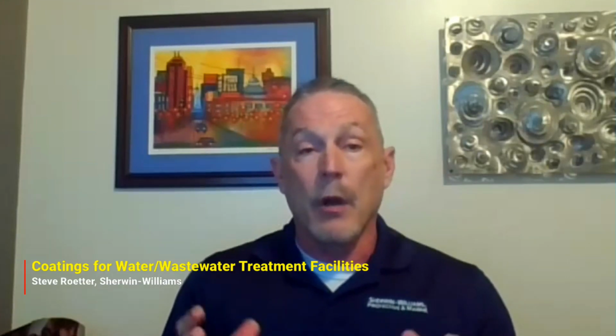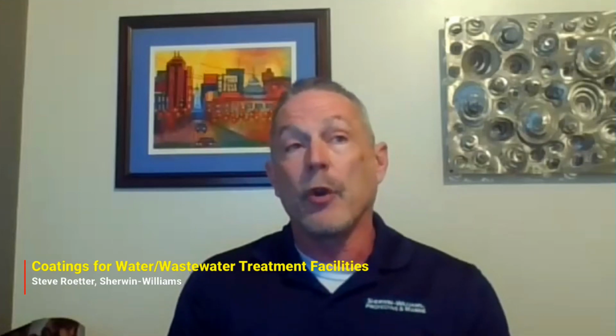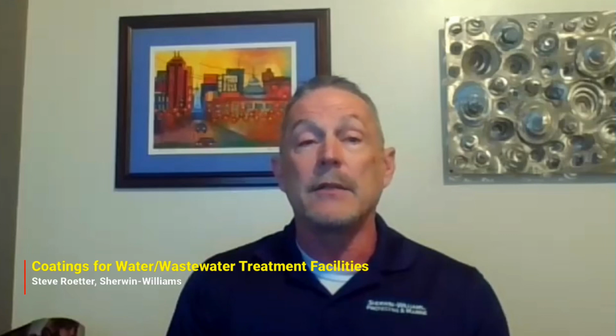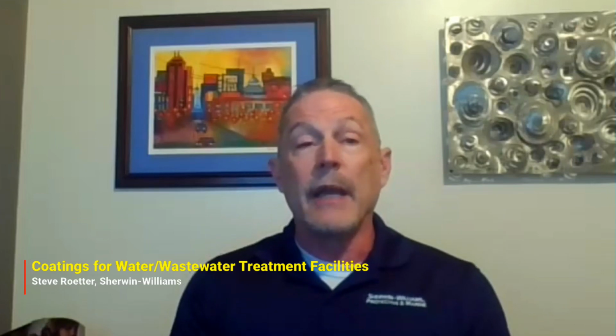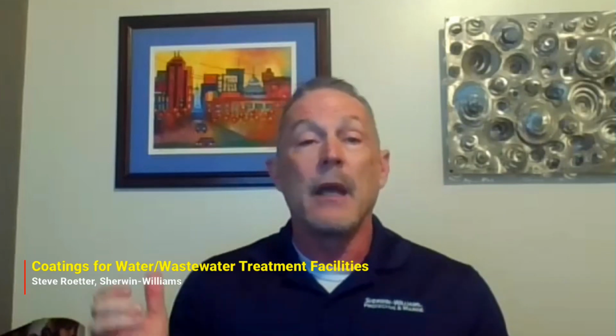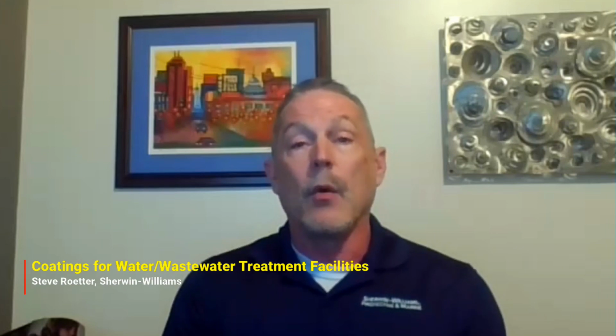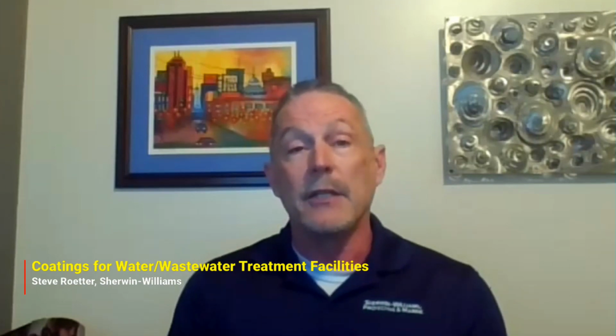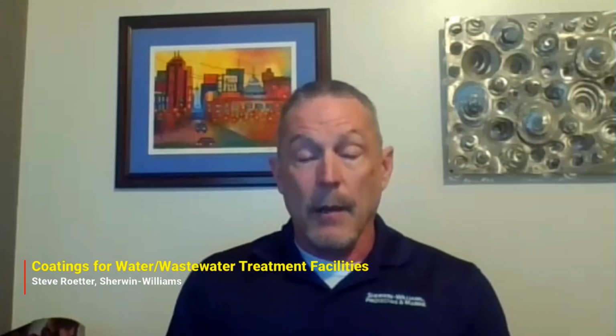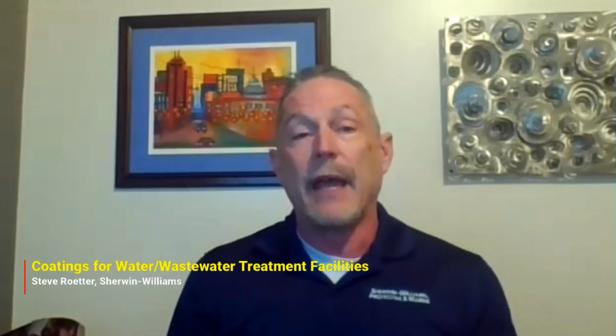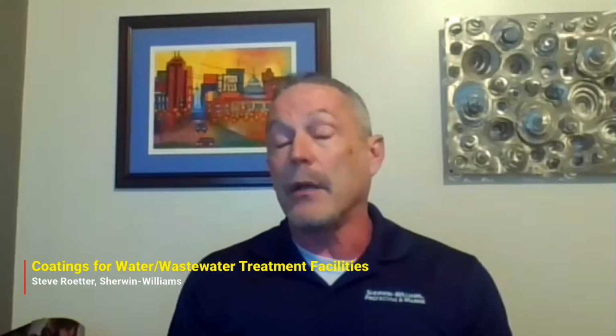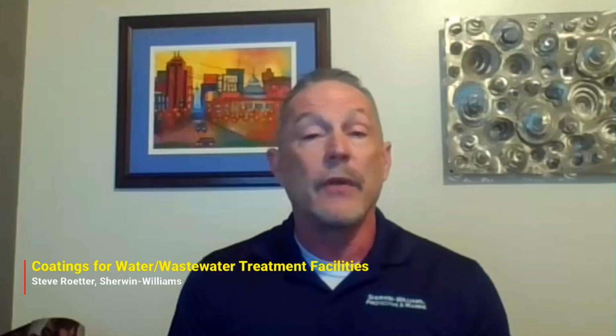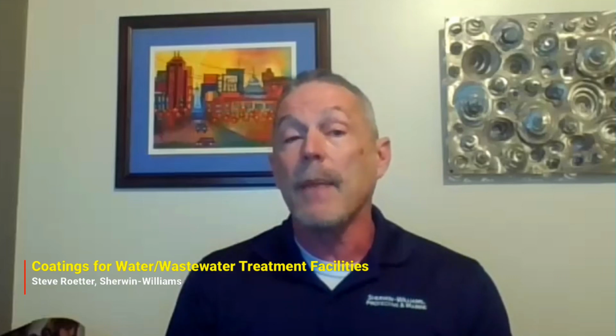With respect to Sherwin-Williams, our number one offering in this space right now is what we call our DuraPlate 6000. That's a 100% solids epoxy. It's glass flake reinforced. And the nice thing is right now it's the only 100% solids epoxy on the market that can be sprayed via conventional spray equipment or brushed or rolled, in addition to the plural component application. So it opens up a lot more contractor options when you don't have to have the plural equipment to put it on. You can get up to 250 mils in a single coat application with it. Return to severe wastewater service in 10 hours.